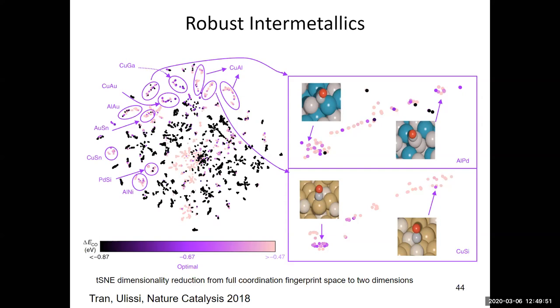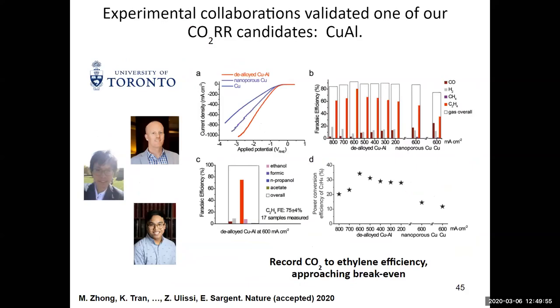We have a large number of different copper-containing compositions and other ones like platinum silicon and copper tin that also look quite interesting. We took this list to Ted Sargent's group at the University of Toronto, and they tried a bunch of these. And I think we got a little bit lucky on this. Copper aluminum turned out to be very active and very selective for making ethylene. I think we were lucky because nothing in the models I showed you said that we should make ethylene. All I can say is that it's probably going to make some C1 or C2 product and not make hydrogen. I wish I could predict that selectivity. That's something we're working on now, but that's really hard.